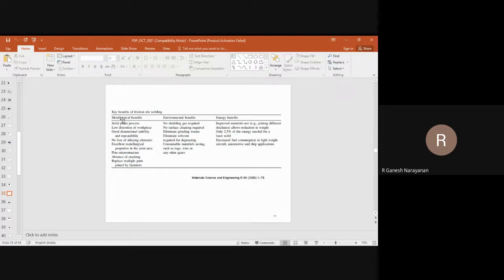Metallurgical benefits are shown here: low distortion of workpiece, good dimensional stability, good repeatability, excellent metallurgical properties, fine microstructure. Environmental benefits: when compared to fusion welding, there is no shielding gas here, no surface cleaning required because anyway the surface will get deformed. No wastage, no solvents for degreasing. So all these things can be avoided. Energy benefits: improved material use. It can have different thickness, and weight reduction is possible. It is said that only 2.5% of the energy needed for laser welding is used here.